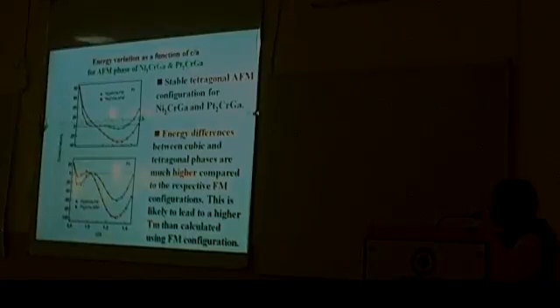This is also evident here for the Ni system and the Pt system - the energy difference between cubic and tetragonal phases is much higher compared to the respective FM case, seen from these two plots. This is likely to lead to an even higher transformation temperature than calculated using the FM configuration, which I showed earlier in my table.